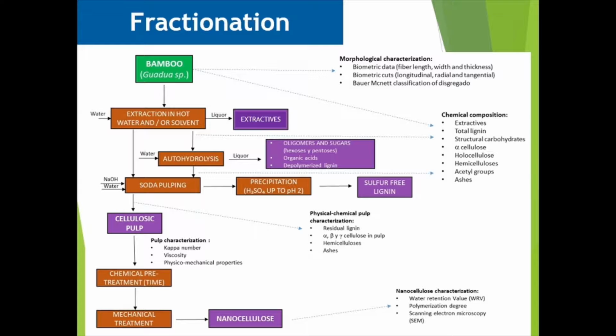Both bamboo species were treated with hot water to remove extractives. These treated samples were divided in two parts. One part was treated by autohydrolysis hydrothermal treatment to extract the hemicellulose before the delignification, and the other was delignified directly. The delignification was carried out by soda and anthraquinone pulping.